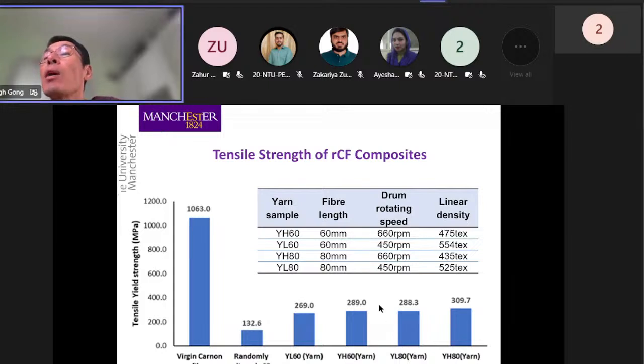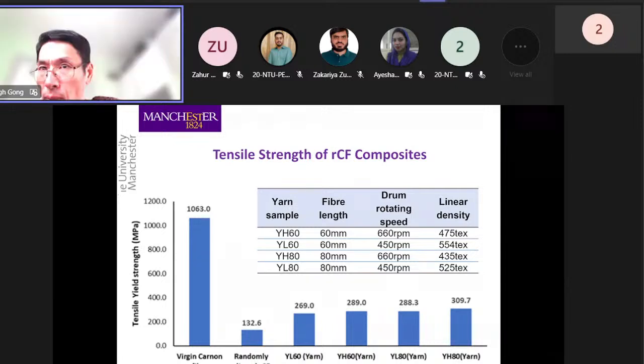The other thing is that with the increased drum speed, obviously, like in any yarn production system, when the twist increases, the yarn becomes tighter. So that helps to make the yarn more compact, getting better strength out of it. But if you look at a straight comparison, you will find the composites made using spun yarns are still much lower, about a quarter to a third of composites made from virgin carbon fibers.